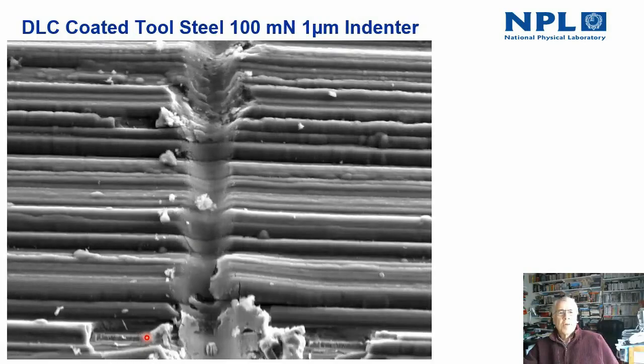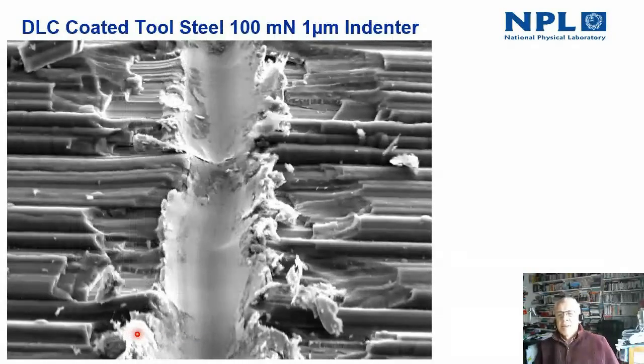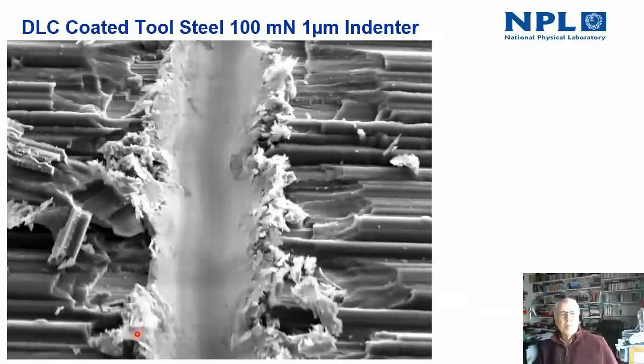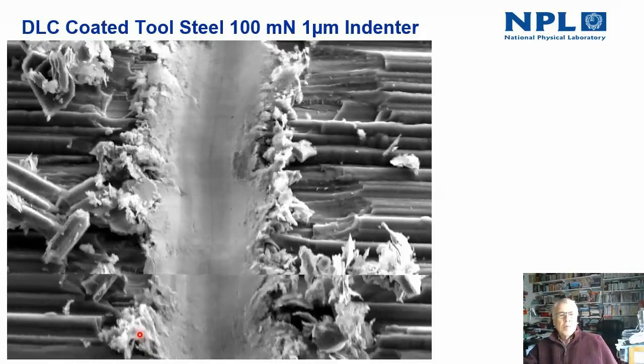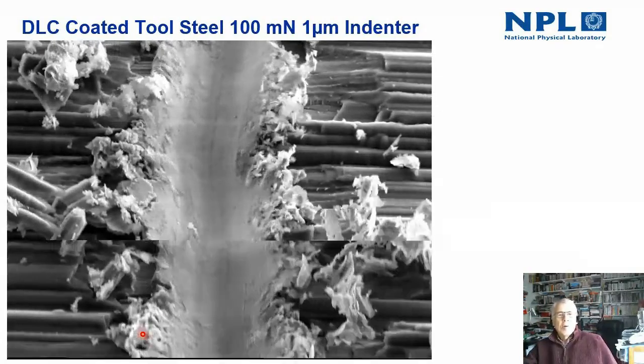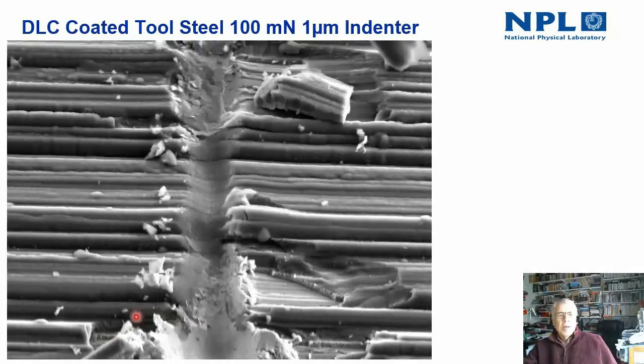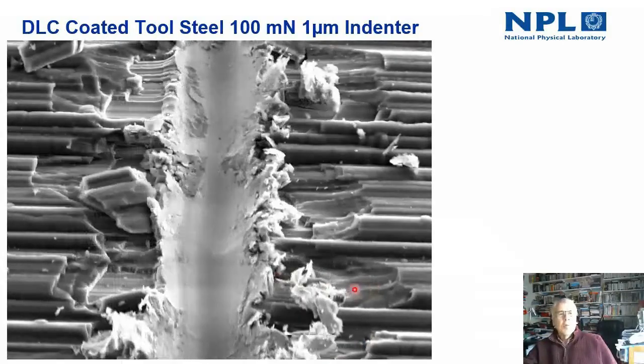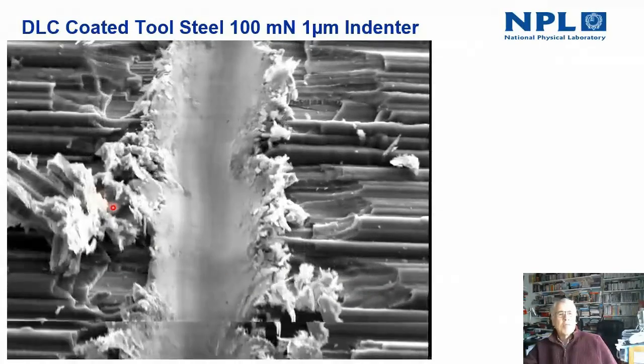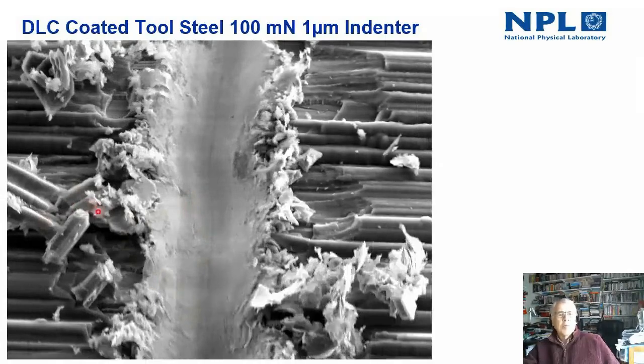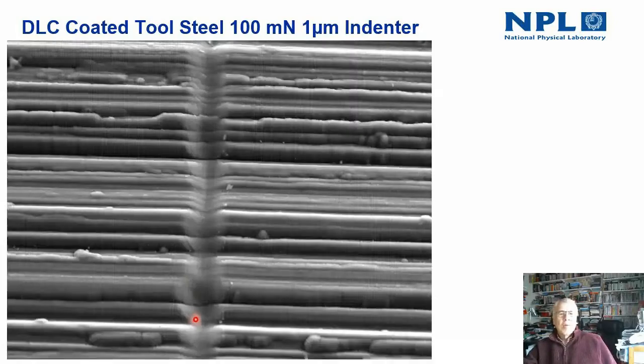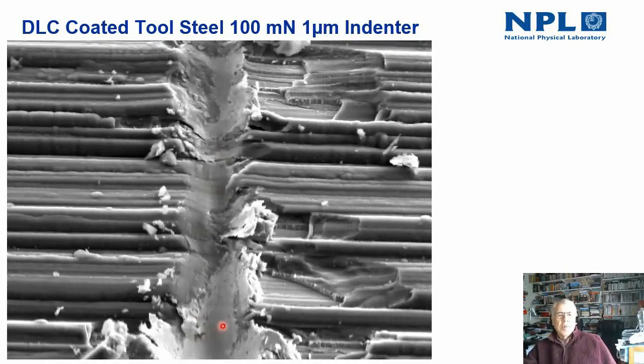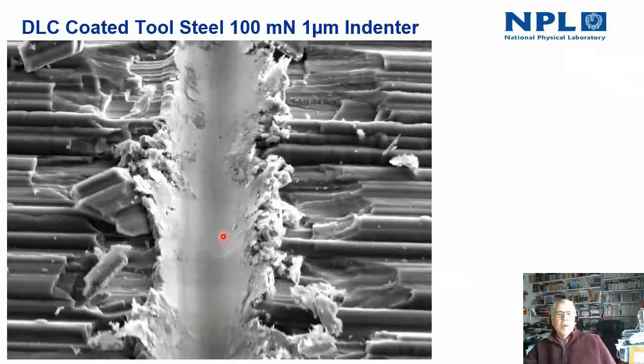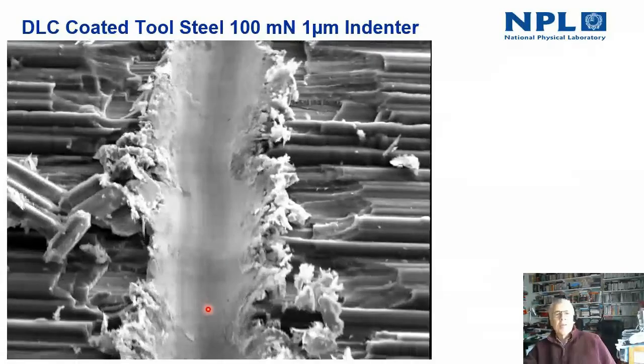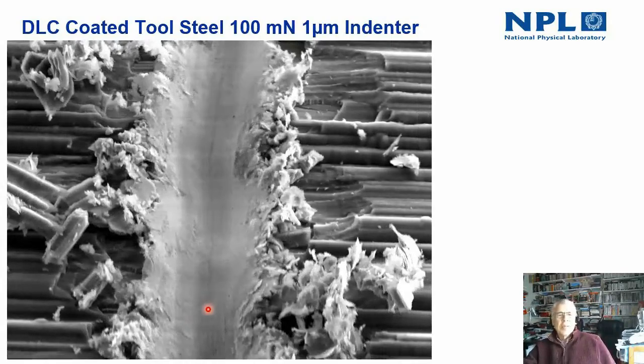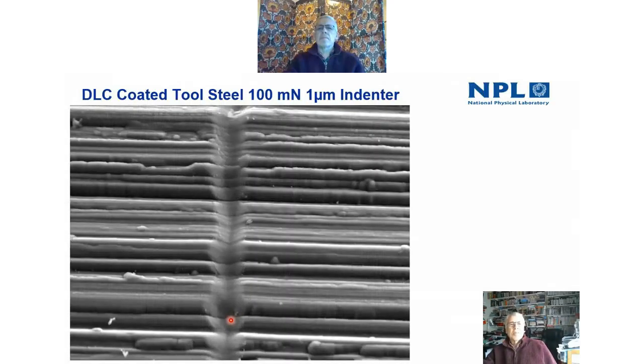This contrasts with the behavior in this experiment, which was carried out under exactly the same conditions, on the same sample as the previous experiment. But here, after the first pass or so of the indenter over the surface, you got totally different behavior. So here you can see fragments of coating have just been removed from the surface, and here you see a fragment in motion as the indenter repeatedly moves backwards and forwards over the surface. You can also see in the base of the scratch here, as the scratch develops, that there's a lighter area of contrast, and this is where the coating has been removed completely from the scratch, and it's showing the underlying substrate underneath the coating.